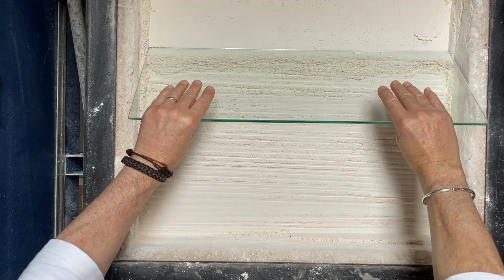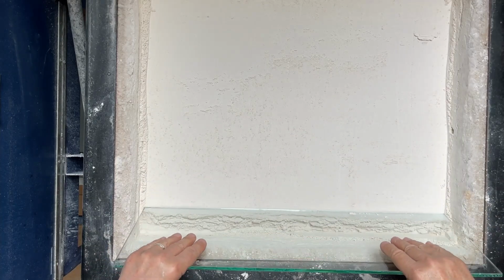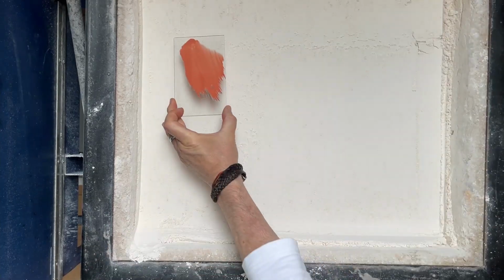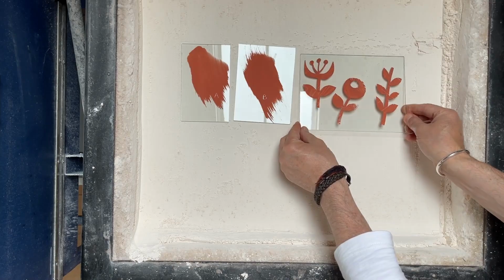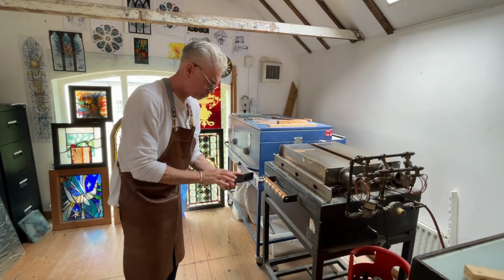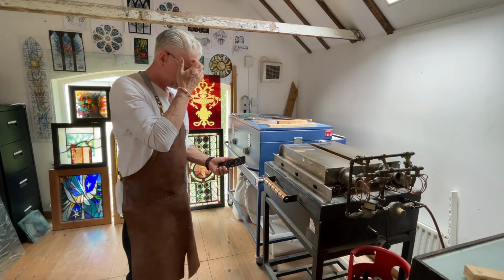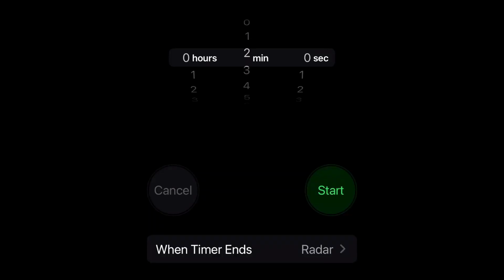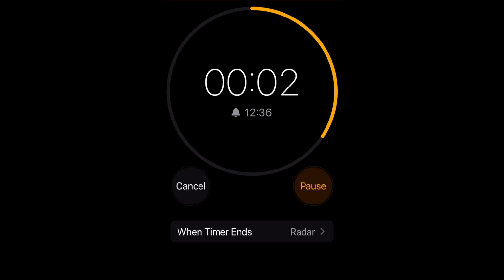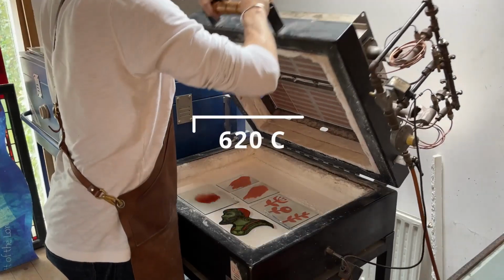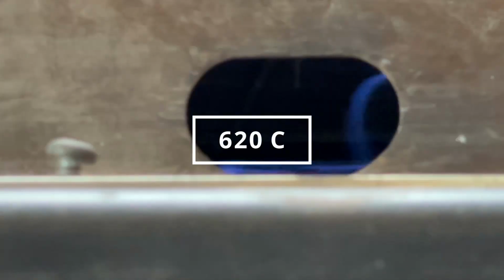Here's what you might want to try to help you get great results with yellow stain. Yellow stain is notorious for being quite difficult to work with, and so it's important to do a test firing with the intended glass to make sure it takes the stain well. I fire the yellow stain in a particular way to get the best results. This technique requires you to have a stopwatch at hand, as you'll be firing the stain for exactly 2 minutes once it's reached the correct temperature of 620 degrees centigrade.